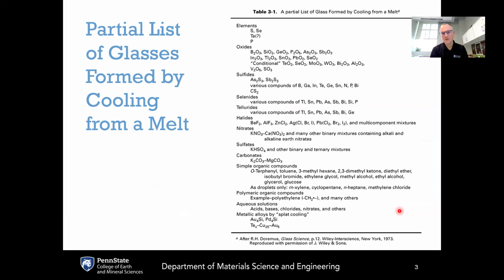This table, which is table 3-1 in the book, lists just a small sampling of different types of chemistries that can be formed into glasses by cooling from the molten state. There are certain elements here. So selenium, out of the entire periodic table, selenium is actually the best elemental glass former, although sulfur, tellurium, and phosphorus can also be cooled into the glassy state without crystallizing. Of course, many different oxides are very good glass formers, like boron oxide, silica, germania, and so on.